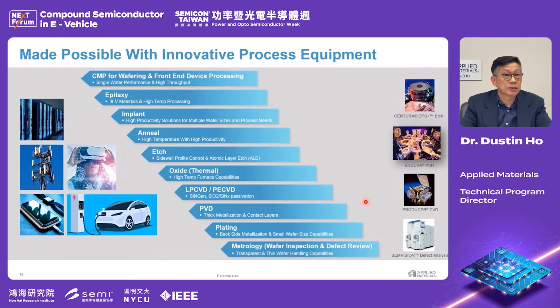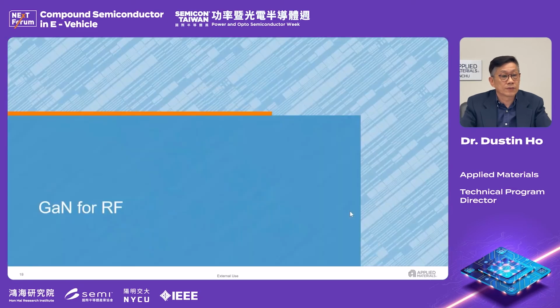And here is the process equipment for the GaN process. So you have the CMP and the MOCVD for the epitaxy, and you have the implanter for the isolation and the gate doping, and the annealing. In the gate etch, especially the high-selectivity ALE for the GaN etch, and then some oxidation furnace, and then you have ALD or LPCVD for the isolation, then PECVD passivation, PVD metallization, the plating, and again the metrology for inspection and defect review.